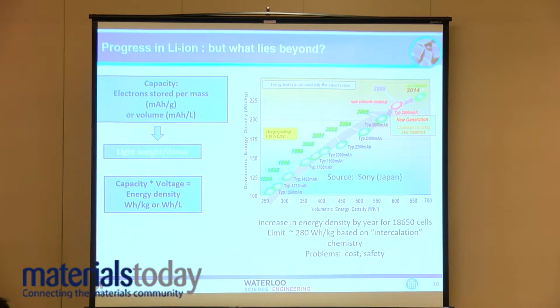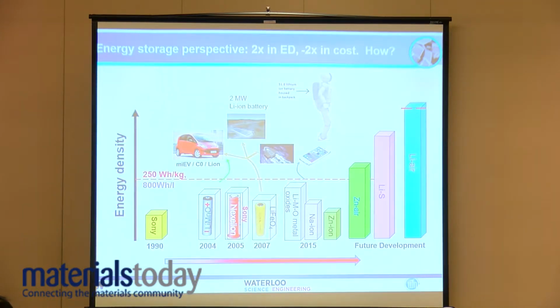And in any cell, whether it operates by intercalation or it's a lead-acid battery, we have the electrons stored per mass, which is usually coulombs per gram, or we can also count that in coulombs per liter, which would be a volumetric energy density. And this is particularly important, and it's a concern for nanomaterials, because we don't want massive cars with a massive battery. So these batteries, especially for automotive transport, have to be fairly dense. In other words, they have to have a good volumetric energy density.